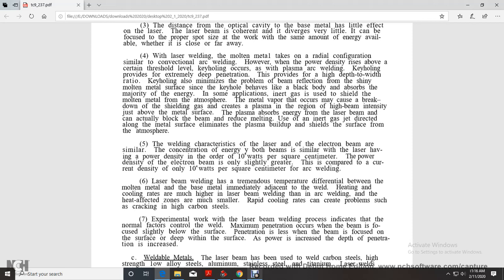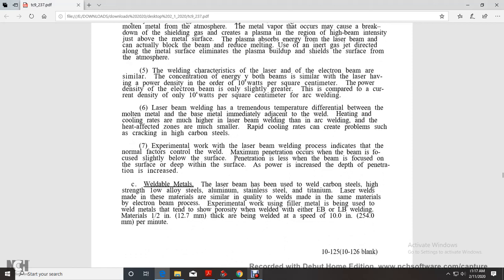Since the keyhole behaves like a black body, it absorbs the majority of the energy. In some applications, inert gas is used for shielding the molten metal from the atmosphere. Metal vapor that occurs because of the breakdown of the shielding gas creates plasma in the region of high beam intensity just above the metal surface. The plasma absorbs the energy of the laser beam and can actually block the beam, reducing penetration. Using an inert gas jet directed along the metal surface eliminates plasma buildup and shields the surface from the atmosphere.